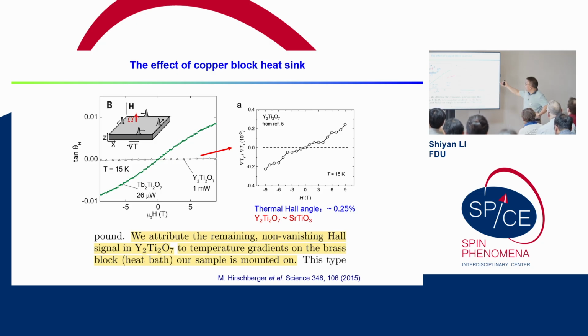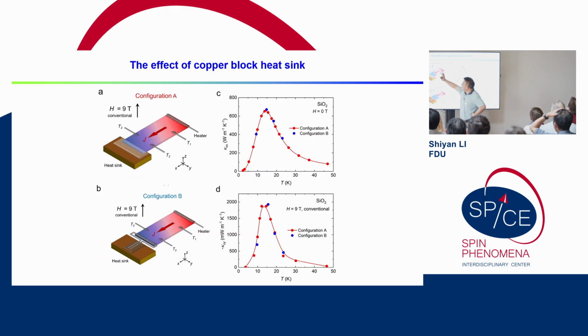Then if this is true, that's against our claim of universal phonon thermal Hall effect in all crystals. But actually, this effect from the copper block, the heat bath, Louis Taillefer's group already checked and excluded this effect. We also check it, because usually in the measurement we just put this sample onto this copper block. But then if there is some temperature gradient from the heat sink, maybe there is some contamination. So now we choose another configuration. We use thick silver wire, just connect it at almost one point to this heat sink, and we observe similar results for these two configurations.